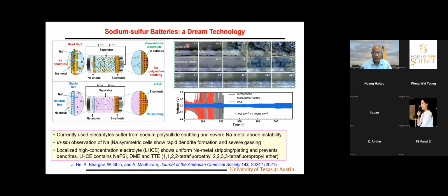Few things here. In the first two cases, we see more gassing, and we also see more dendrite formation compared to the localized high concentration electrolyte, and more importantly, more overvoltage. In the case of the use of LHCE, we get much better symmetric cell cyclability compared to the other two cases. So again, I talked a lot about electrolyte in the case of high nickel layered oxide cathodes. Clearly, electrolyte plays a much major role in all these systems compared to the cathode or anode itself. So just the electrolyte change, everything else is the same here.